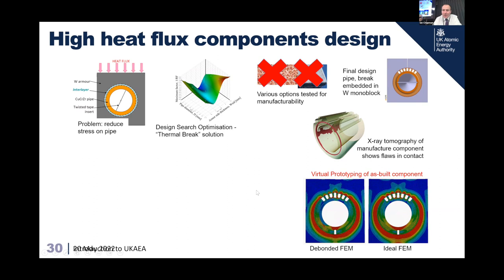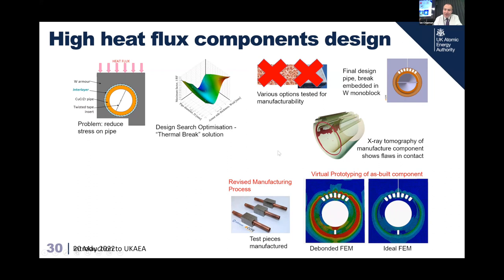And that millimeter, which sticks out, will then get all of the heat, will hit that tiny little corner, which is exposed, and it'll just melt. So you'll then end up with molten tungsten running around the inside of your machine, which is not a great place to be. So instead of putting that in a heat flux test facility, we just redesigned it. So we came up with a better way of manufacturing it, and then it worked fine.